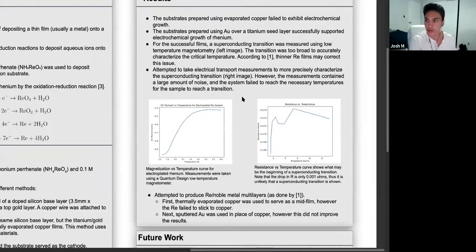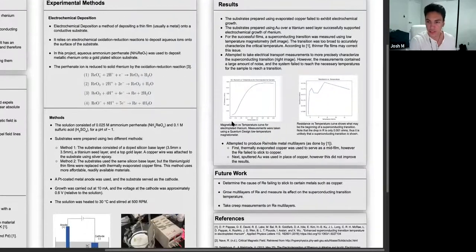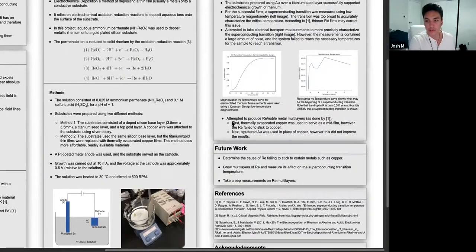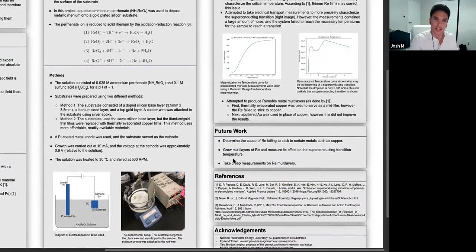Aside from our single layers, which we tried to characterize with measurements, we attempted to produce multi-layers of rhenium and a noble metal, which we used both gold and copper. This was something that was studied previously by a different group, and we were trying to replicate their results. Unfortunately, we couldn't get the rhenium to stick when trying to do multi-layers. It kind of grew around the sides, and we didn't get clean films doing that.